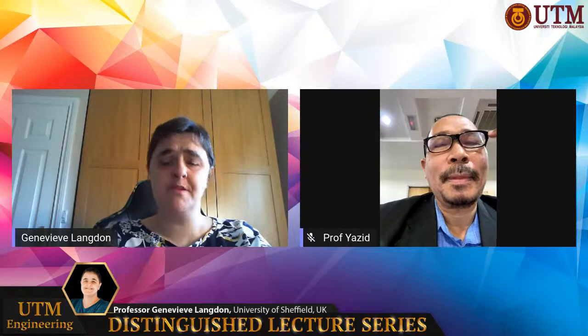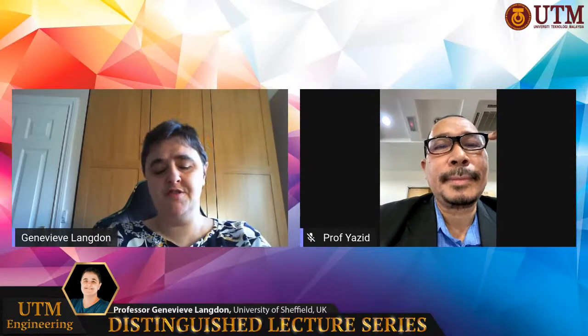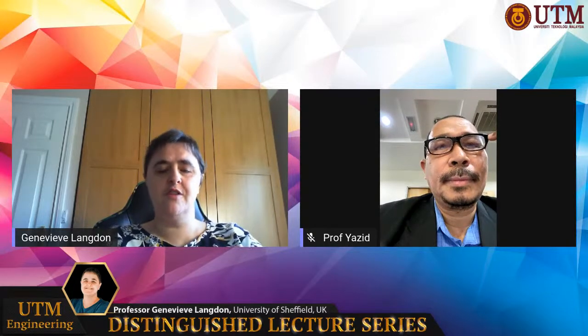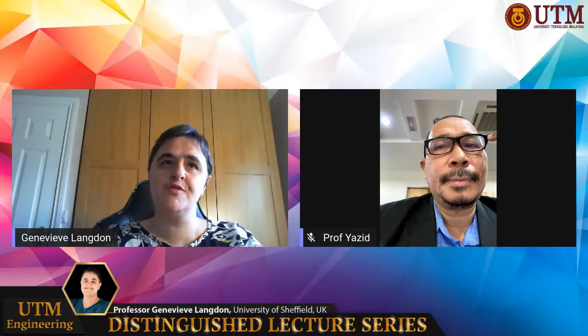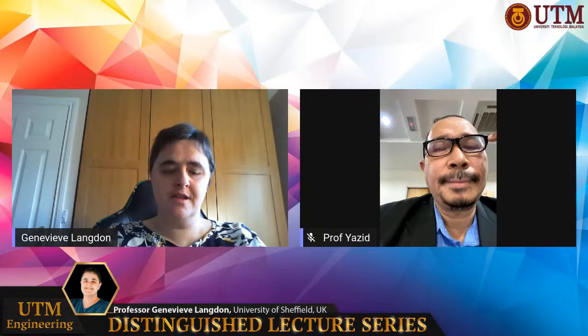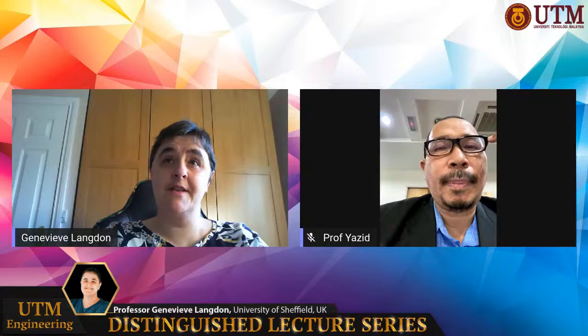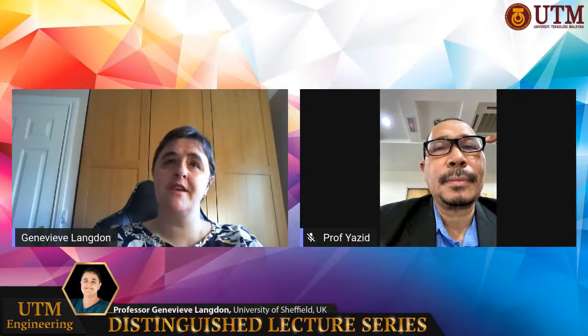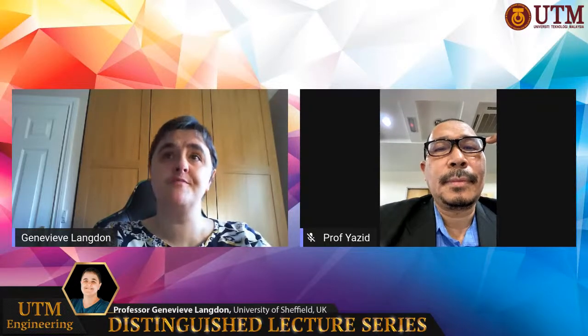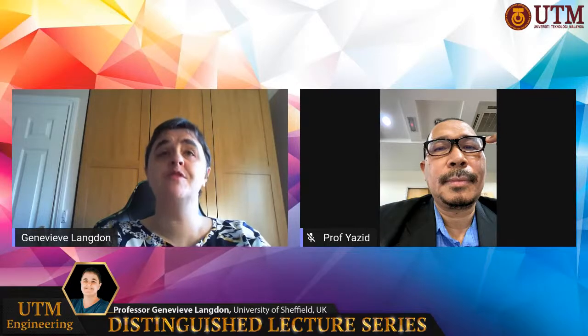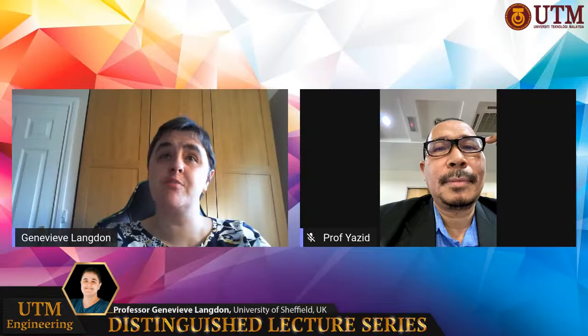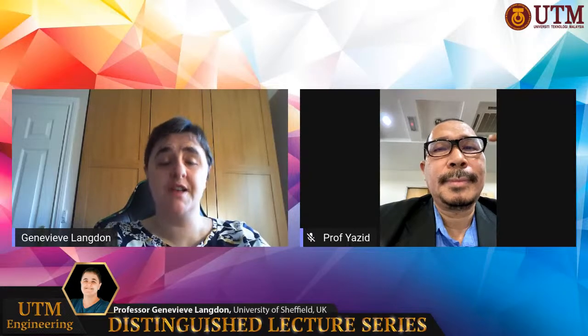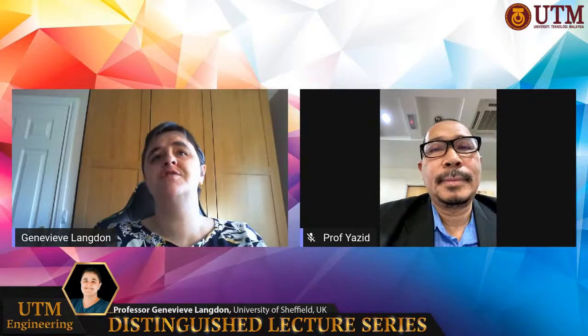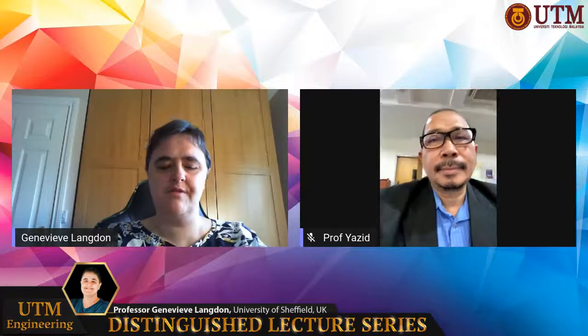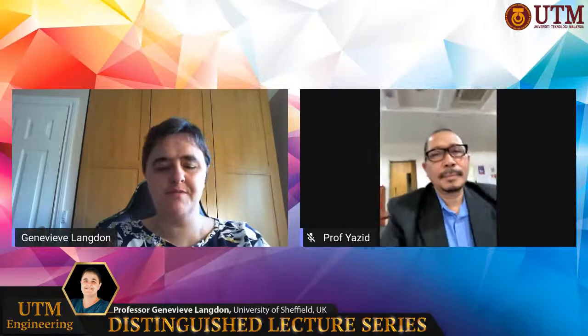If you do the same thing in a blast experiment, then first of all, you've got a compressive stress wave that moves through the composite layer into the metal layer and then bounces back as a tensile wave and can spall the back face off. So that's one of the things that you need to look for, this effect of this massive stress wave that propagates through the materials, as well as the lateral ones that are going transversely through the fibers, etc. You do have this compressive one that bounces through.